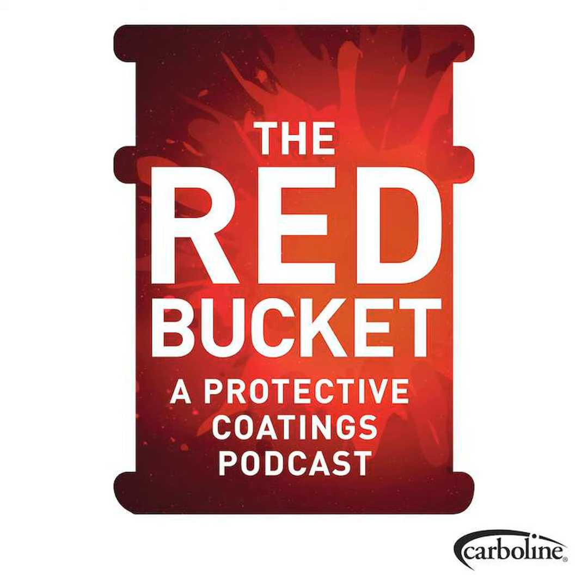You've got edge retention and you've got flow and leveling properties. And when you're talking about a lining, these are generally two opposing features. You don't typically have both, where you either have good flow and leveling characteristics or you have good edge retention. But oftentimes you don't have both because those two features oppose one another. And in order to flow well, you typically don't have good build and edge retention properties. So this is why it's important to get that coating applied uniformly by uniforming out the substrate by doing that blending.